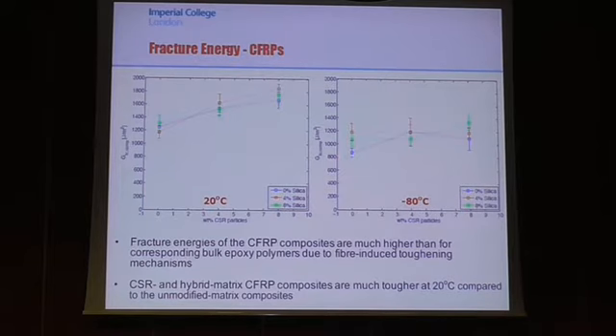At minus 80 degrees, this is our control. Here we have a drop in fracture toughness of about 300 joules per meter squared, down to about 850, and adding in the modified matrices causes an increase in the fracture toughness, but it's difficult to figure out whether there's any benefit in adding in hybrid materials, because they all seem to just be independent. Adding the tough matrix just appears to be independent of the amount of CSR particles or silica particles that you add.